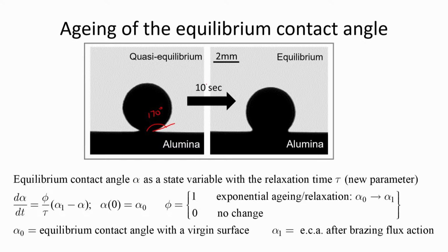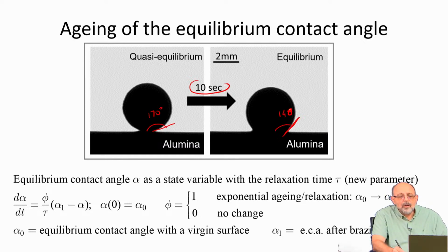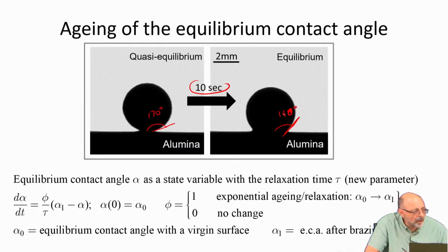And then after approximately 10 seconds, this contact angle deteriorates to 140. So this is equilibrium, but this involves some chemistry. There is aging of the contact angle.